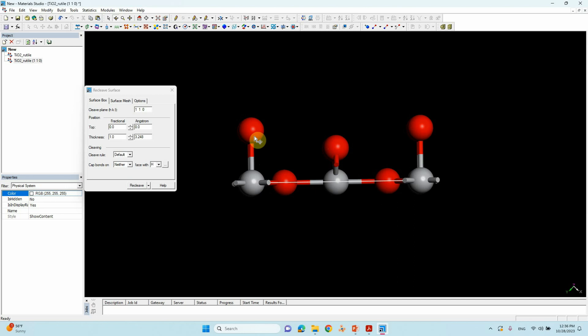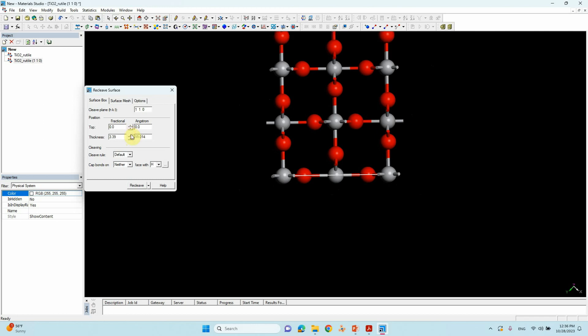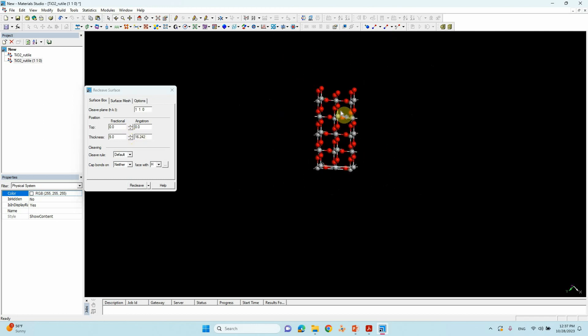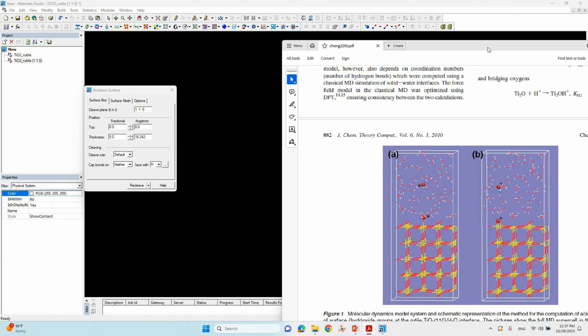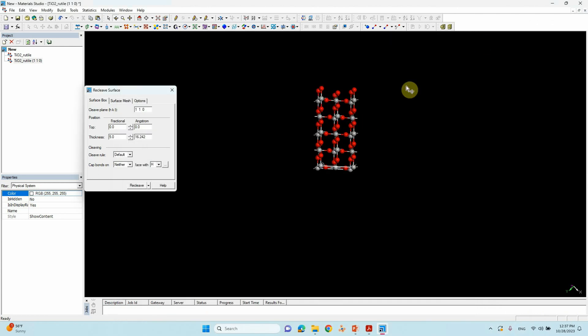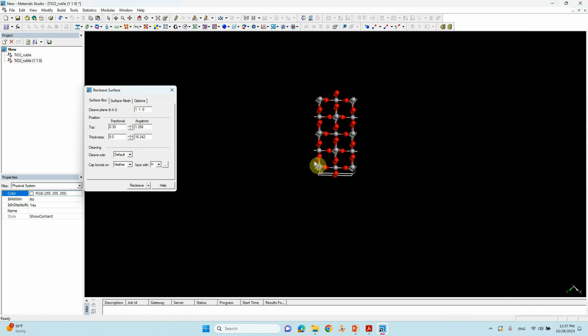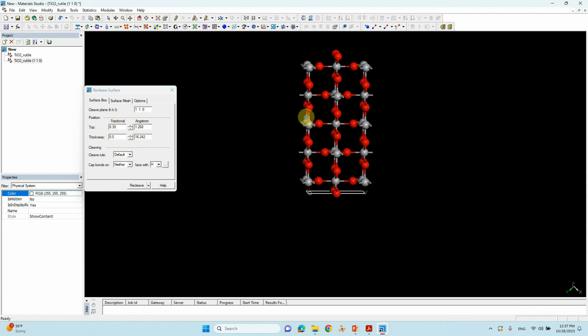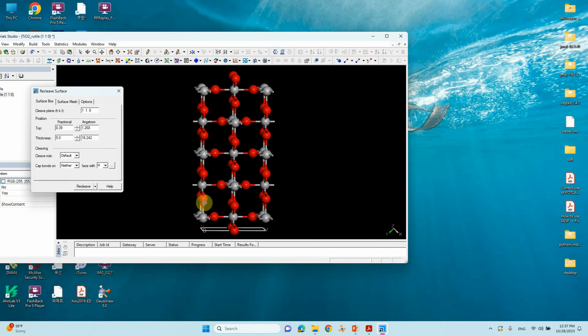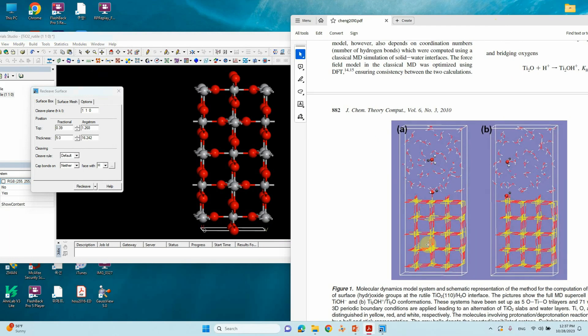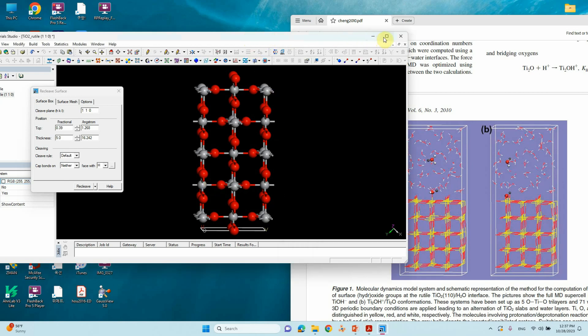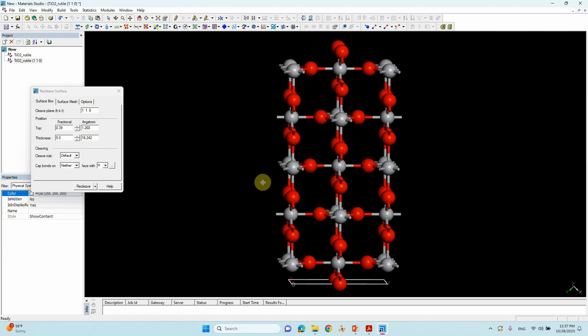I will set it to get a result similar to that paper. I'll use 0.39 for the fractional position — you will get a structure similar to that paper. We haven't made the supercell yet; if you make the supercell it will look similar. So we have made the slab.